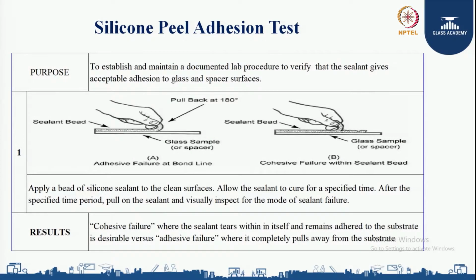Next is the silicone peel adhesion test. Its purpose is to ensure bonding or adhesion between the glass, silicone, and spacer, so the sealant gives acceptable adhesion to the glass and spacer surfaces. The procedure is to apply a bead of silicone sealant to the clean spacer surface, allow the sealant to cure for a specified time, then pull out the sealant and visually inspect the mode of failure.